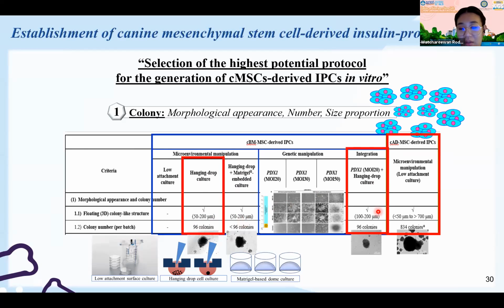Another method that can get the colony is the integration method of the bone marrow mesenchymal stem cell, which is still able to get just 96 colonies. And the last one is the microenvironmental method to induce the canine adipose mesenchymal stem cell into IPC using the low attachment cell culture dish. We found that we can get around 800 colonies per time. So only three methods are going to be chosen for the next step.